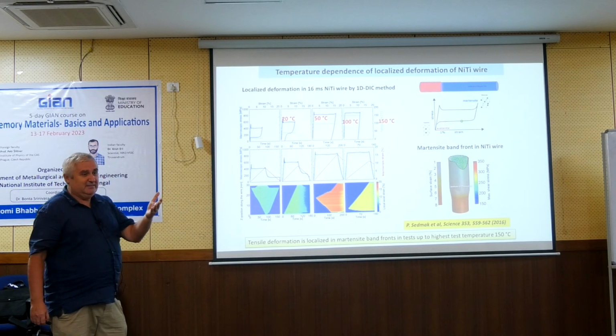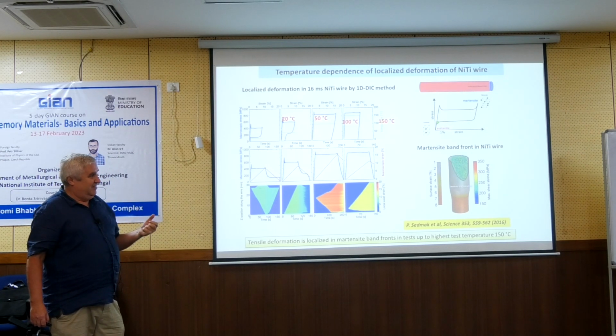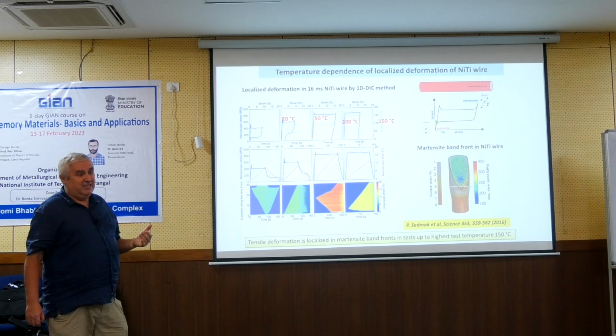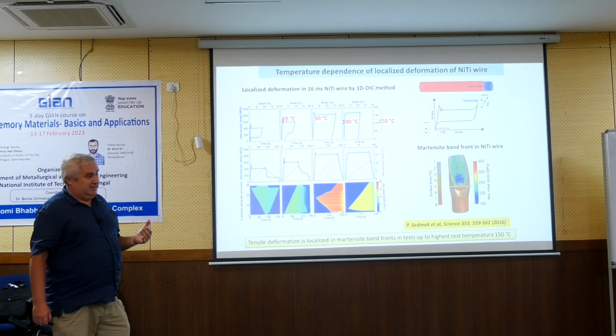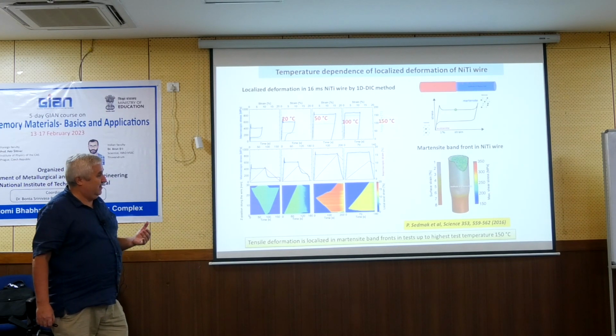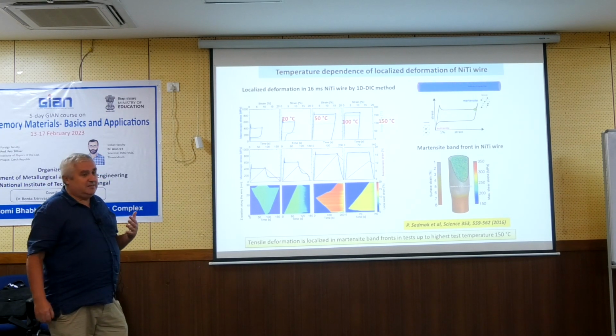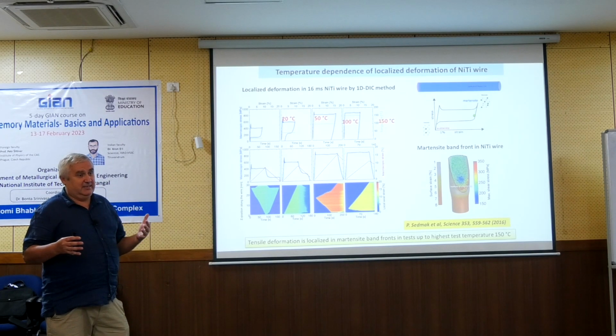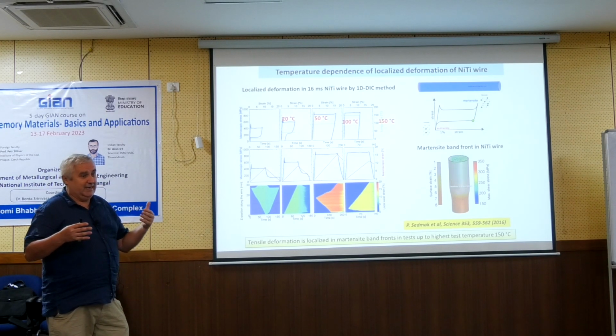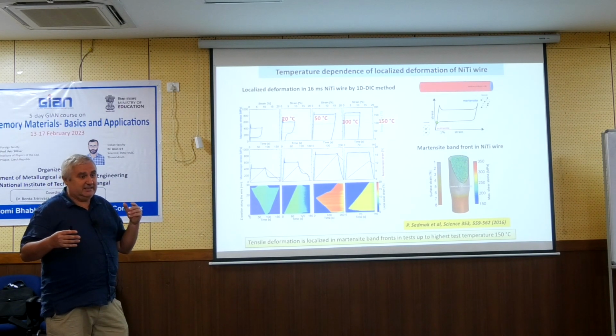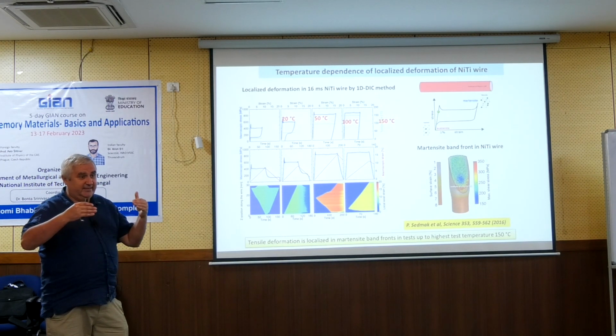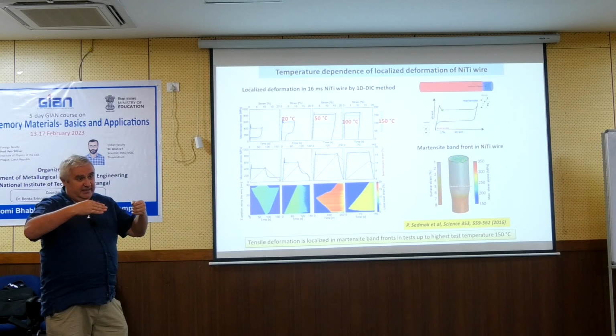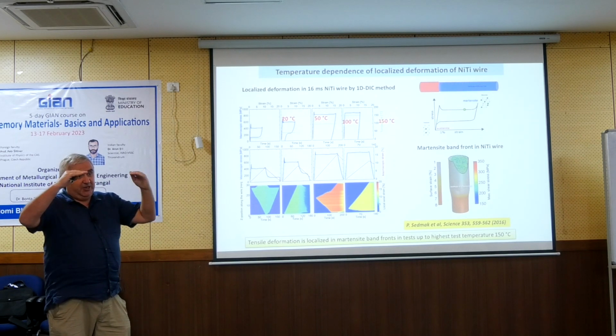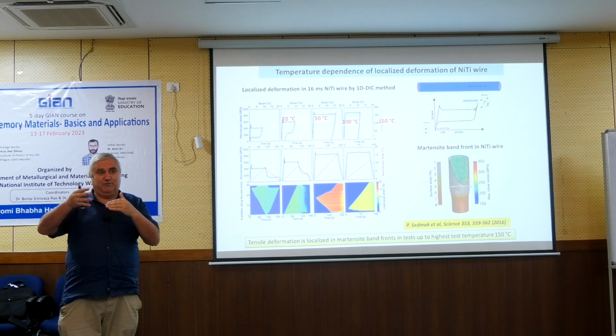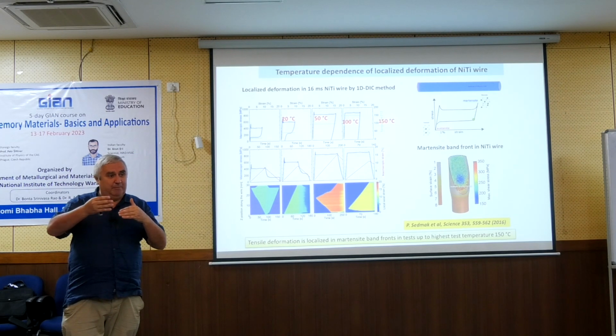This is also a very frequent question, about strain rate. My opinion, based on my experience, is that superelastic deformation is rate insensitive. The only problem is this latent heat. Because you have the latent heat, if you do it quickly, the latent heat cannot go out of the specimen, and the temperature increases. So this is because of thermomechanical coupling with the environment.